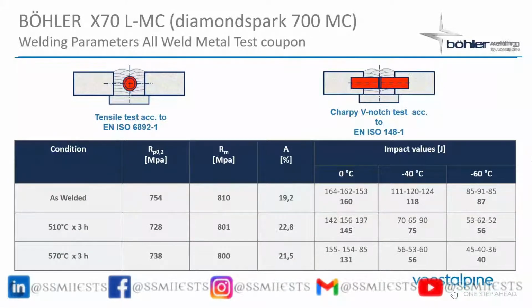Yeah. So these are the all-weld test coupon details. This is just one result, but to give you a perspective from a welding consumable development point of view, we need to do many such tests in our laboratory to actually prove these consumables before they are launched in the market. So this is just one of the tests. Here we did it in an as-welded condition, also in post-weld heat treatment at 510 for 3 hours as well as 570 for 3 hours. And these are the results that we got.